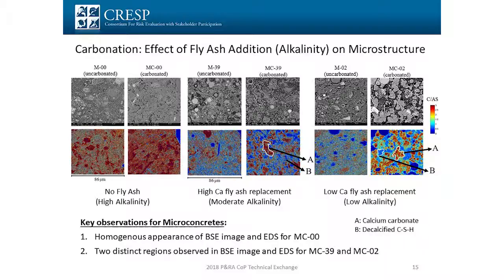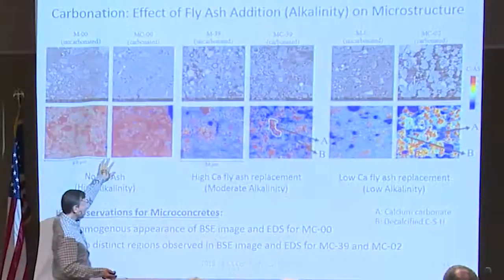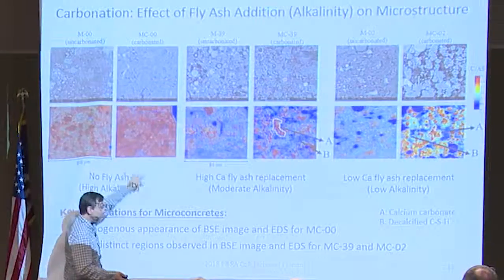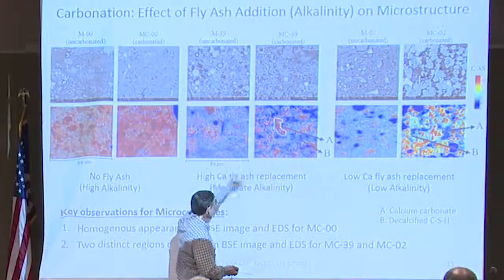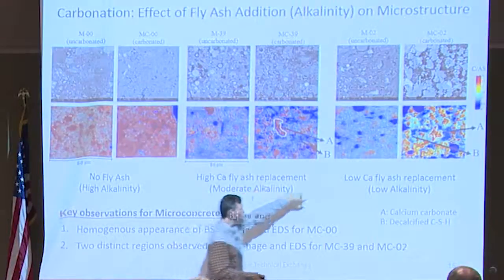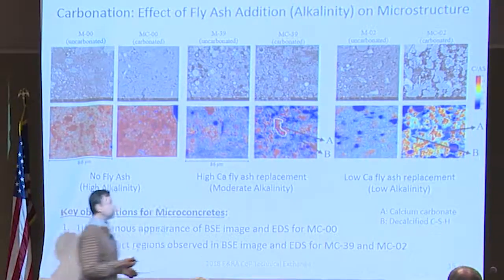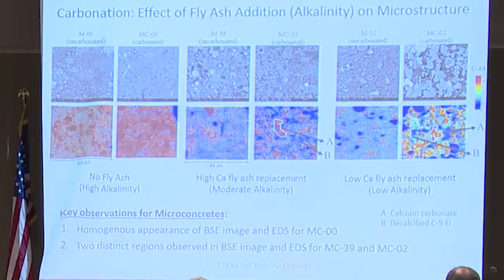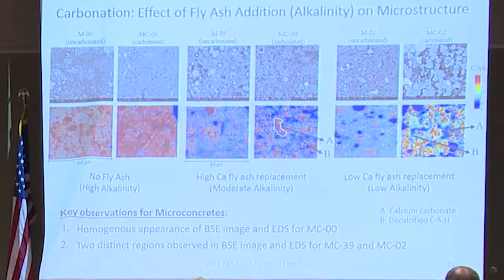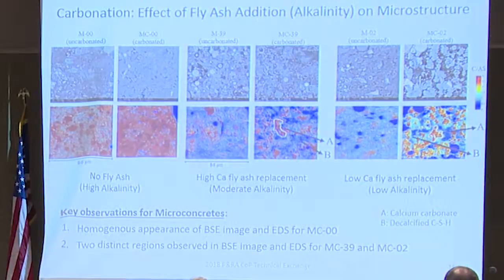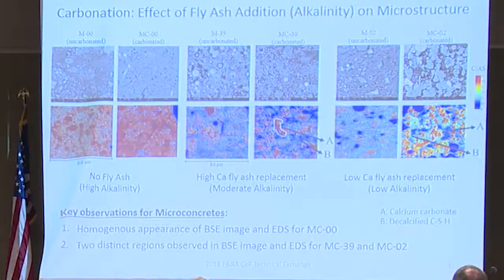These are small scale scans of the material that will show that you do get some definite changes. The one on the left is the uncarbonated, and then it shows to the right of each the effect of carbonation. And you can see also the alkalinity of the fly ash you've added. So let me explain. The 00 is the one without any fly ash addition, so that's just Portland cement. Then you have the 39, which is the moderate alkalinity one, and then the low calcium fly ash is the 02. So you see the effect not only of the carbonation on the pore structure refinement, but also an effect of how much alkalinity was in the fly ash itself. So it also depends what material you're adding to it as to the response you get.